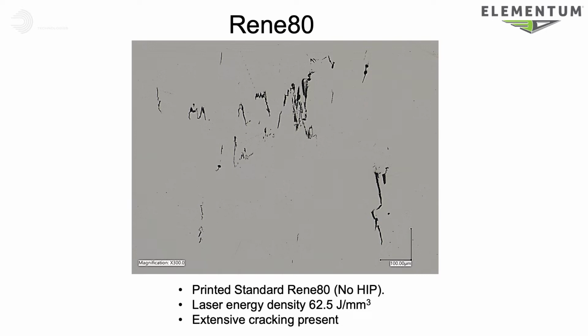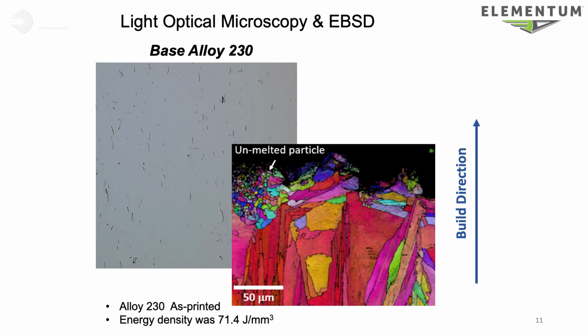Not only are the higher gamma prime alloys challenging though, some of the even solid solution strengthened alloys such as alloy 230 can also suffer from printability challenges. With these types of solid solution strengthened alloys, one of the problems is that you get very columnar grain growth from one layer to the next, and you can get very long columnar grains that suffer from intergranular cracking during the solidification of these alloys.